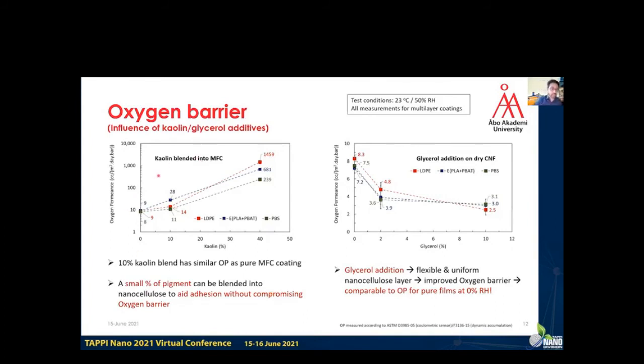On the left we have kaolin blended into MFC, and for 3 different polymer coatings on top. As we go from 0 to 40%, one can see the barrier gets worse. But a 10% kaolin blend has a similar oxygen permeance to that of pure MFC coating. So one can say a small percentage of pigment can be added to improve adhesion without compromising much on the oxygen barrier. And also there might be some applications which do not require a high enough oxygen barrier. So one can replace a little bit of nanocellulose with pigments and save expensive materials.